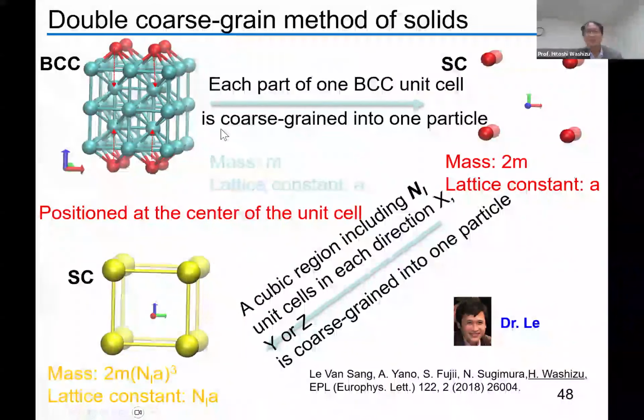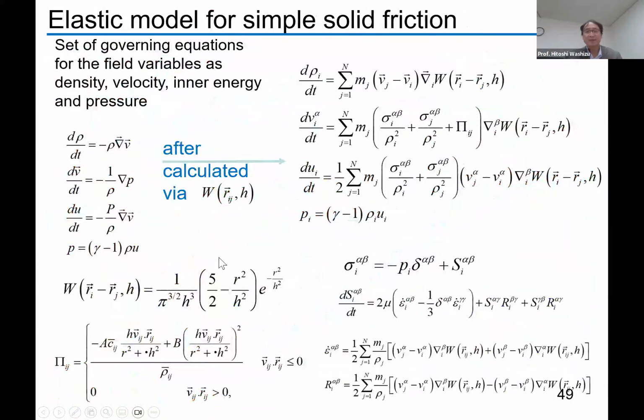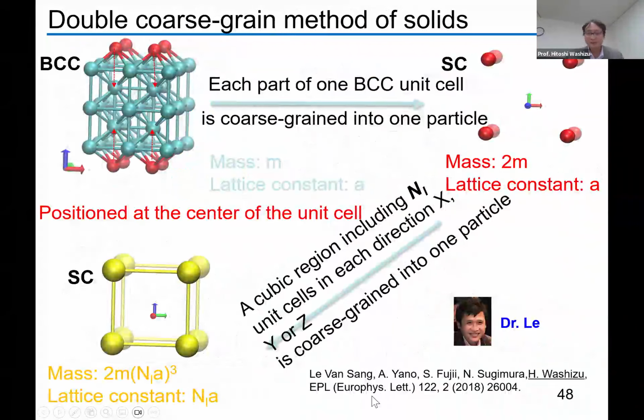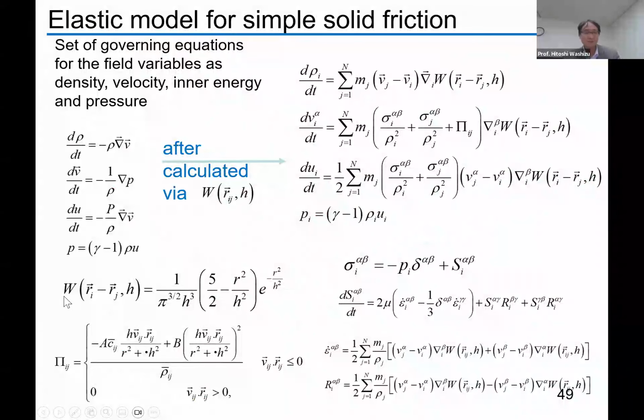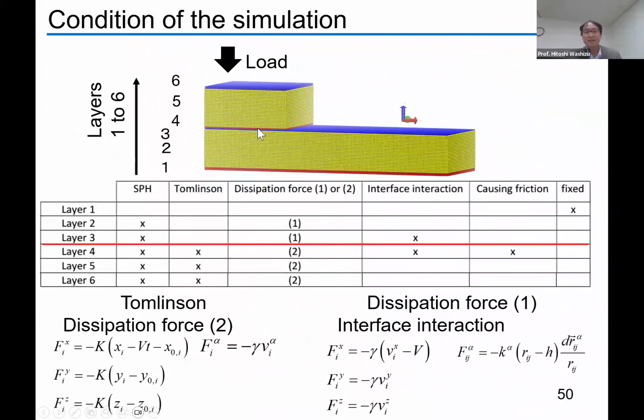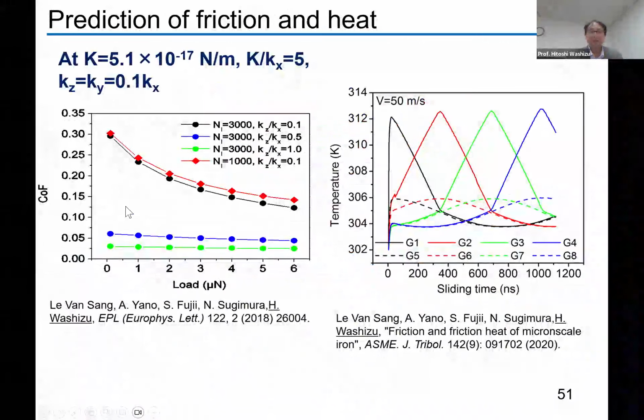All right, so this is an example of making coarse-grained particles of metals, with a first coarse graining and a second coarse graining. Then after that, we use some equations of motion. If you are interested, this paper describes a much more precise method. Finally, we can have this kind of very basic concept model. Here we put some SPH particles, and here some other particles. Then in this red and blue part on layers 3 and 4, we calculate the dissipation force, the Tomlinson force, and some interface interaction like this. And then we have some friction.